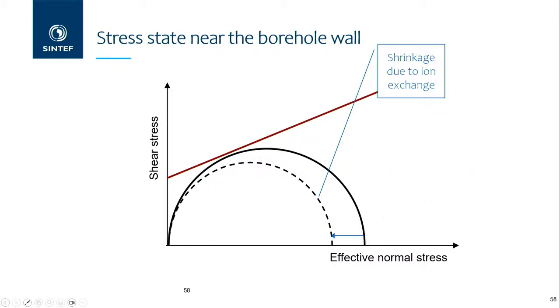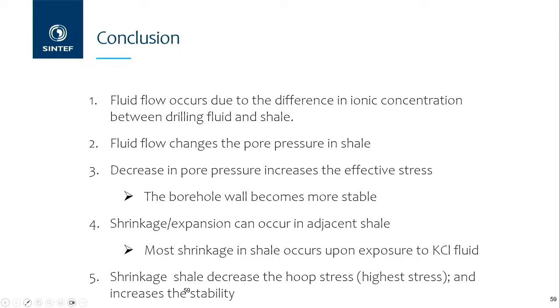Okay, I'm close to the end. So here is the conclusion that I came up with. Even if you don't have any pressure gradient at the interface in the borehole wall, if you have a concentration gradient, you will have a flow. So that's osmosis, and fluid flow can change the pore pressure in shale, and depending on which direction it is changing, you have either a stable borehole or an unstable borehole. And a decrease in pore pressure due to the osmosis with a high concentration of saline on the borehole actually helps to stabilize the borehole wall. And shrinkage also helps if you use KCl. The reason why it helps is because it decreases the hoop stress.